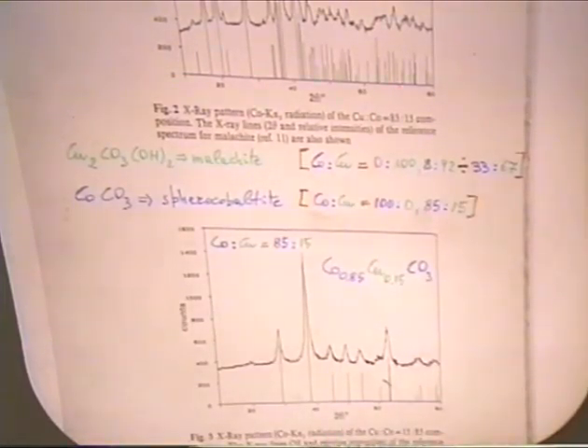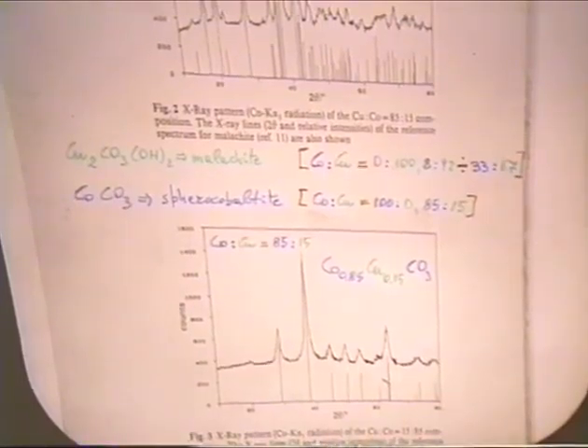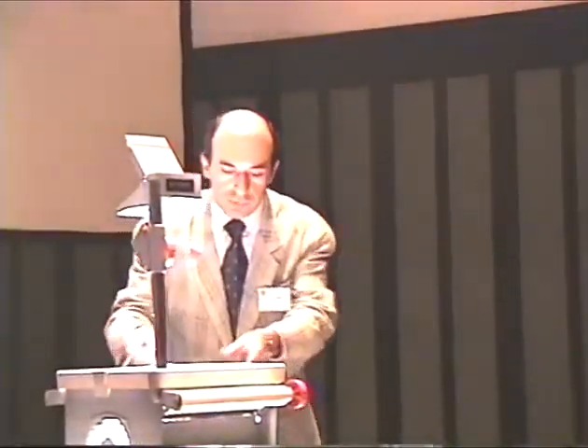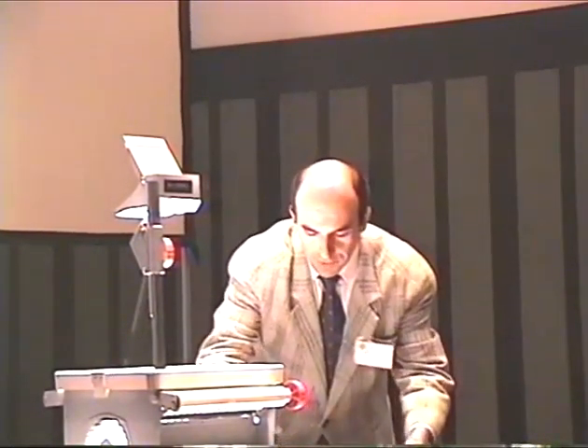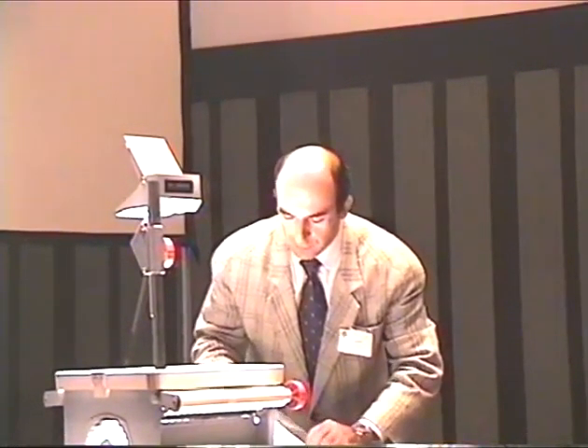So our first aim was obtained. We had the catalyst metal components in the same crystalline lattice. So we obtained, at the end of the preparation, homogeneous precursors. Well, upon decomposition of these homogeneous precursors, we obtained several cobalt copper mixed oxides depending on the treatment atmosphere and on the cobalt copper atomic ratios.